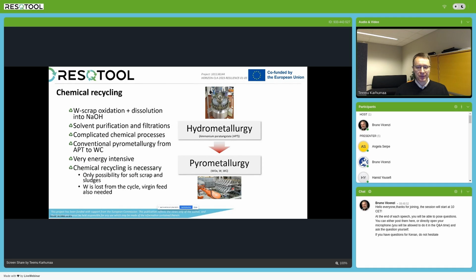And as you can imagine, with 3 different pyrometallurgical steps, and then many hydrometallurgical steps before that, the energy consumption of the chemical recycling is indeed very high. But it is more or less the only method to recycle soft scraps and sludges, or very contaminated tungsten-based secondary raw materials. On the other hand, the quality after chemical recycling is the same as from the virgin raw materials, so high quality and high purity materials can be achieved.